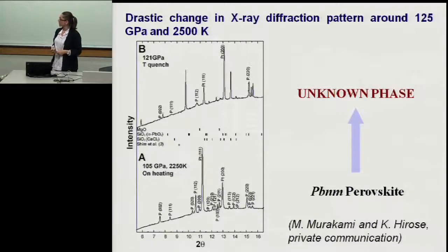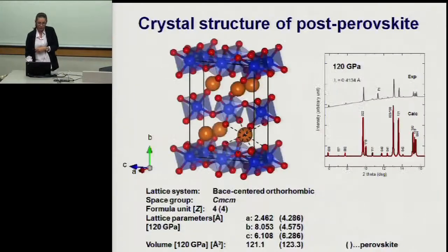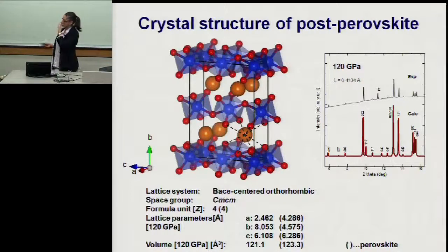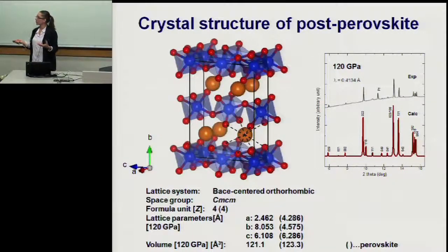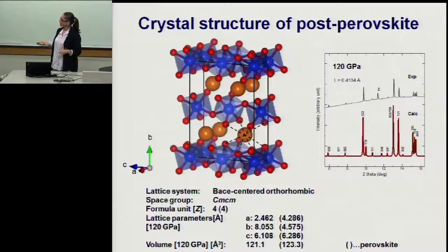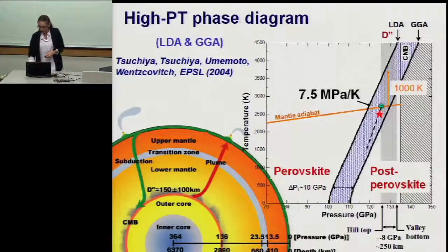We received a private communication from Tokyo that a phase transformation in perovskite had been identified. The structure was not known when we received this X-ray diffraction. And with variable cell shape MD, baking and heating and shaking, we found this structure accidentally. It was pure luck because this structure also could be described with 20 atoms per cell, and that's all we did. That was luck. And we came across this structure. We didn't know it existed, and the X-ray diffraction was pretty similar.